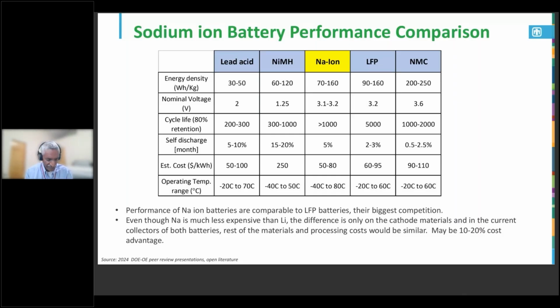Even though there is a big difference in the lithium carbonate and sodium carbonate raw material cost, the amount of lithium in a lithium ion battery is only about 7 to 8%. So the rest of the components are all layered oxides, current collectors, and the separator. So those don't change a whole lot. The difference is in the lithium cost and the current collector cost. So about 10 to 20% cost advantage over lithium ion batteries. Go to the next slide, please.